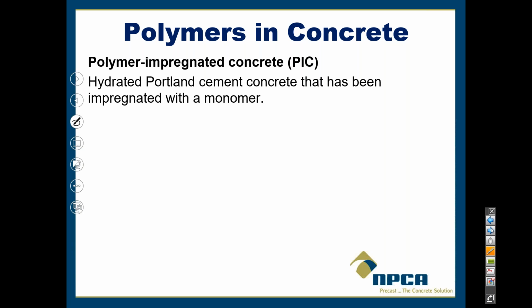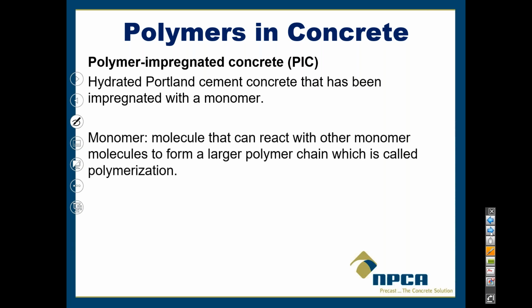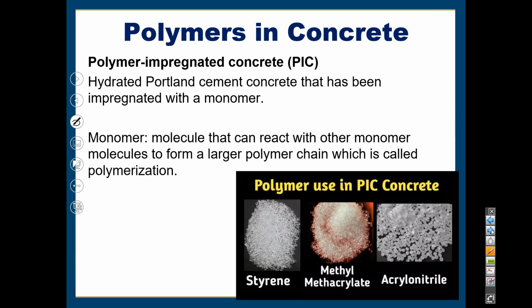So you take this concrete, first of all, you have to dry it. You have to dry it to an incredibly high temperature, because you're trying to dry out all the water that's in the voids, which is kind of a challenge to do. So that would be one of the first challenges, is to dry out those voids. And with the temperatures that you use, you'd have to be careful to not use temperatures so hot that you're melting the chairs in the concrete that are actually holding up the reinforcing. Things like that you'd have to keep in mind, but you're heating up the concrete to get the water out.